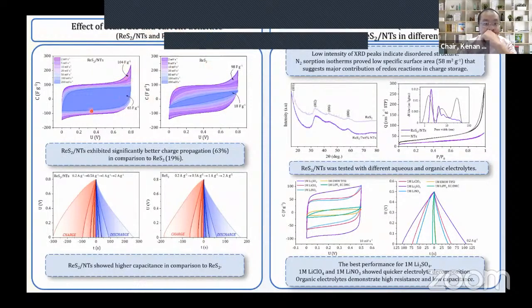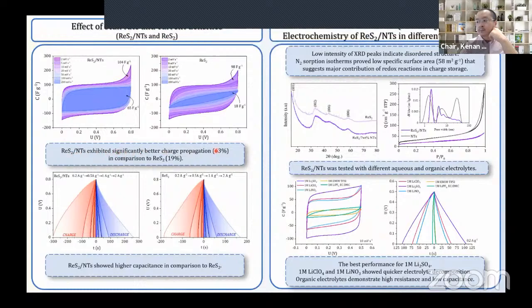And as you can see, not only the capacitance was improved, but also the ReS2 deposited on the nanotubes exhibited significantly better charge propagation, by about 63%. We have proved that we have obtained the demanded structure by XRD, and the nitrogen sorption-desorption proved that the textural properties of this material are very comparable to the raw materials.